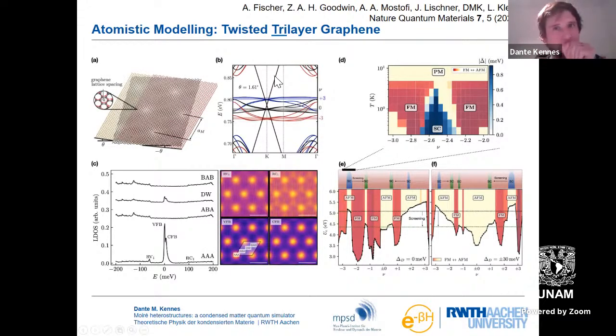And these are works driven by excellent students, Amon Fischer and Lennart Klebel, where they're really trying, for example for graphene, to write down all the pz orbital physics of such a huge unit cell system, and then add the atomistic interactions on top of that, and try to do, let's say, random phase approximation Ansätze on this, or even upgrade that to a method called functional renormalization group. So you see that at a twist angle of 1.61 degrees, for example, you have tens of thousands of atoms in this unit cell, and these guys worked really hard to get an atomistic description of the interaction effects, and this is shown in these two panels here, B and D.